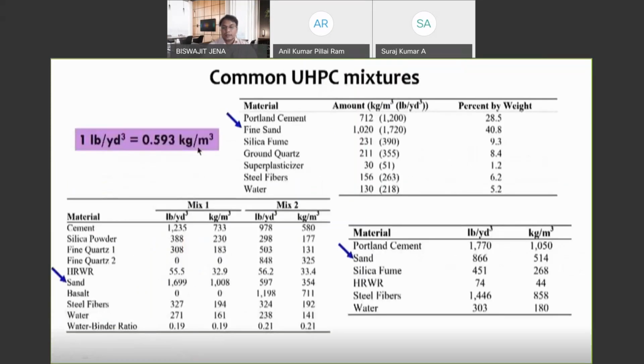Next, we'll come to some common ultra high performance concrete mixes available in the market. So these are mostly commercial mixes. The first thing that you notice is a very high amount of cement. So you need a very high amount of Portland cement for two different reasons. My first one is my water cement ratio is very low, which means only a small fraction of cement is going to be hydrating. If only a small fraction of cement is going to be hydrating, I need more cement to make up enough of the reaction product.